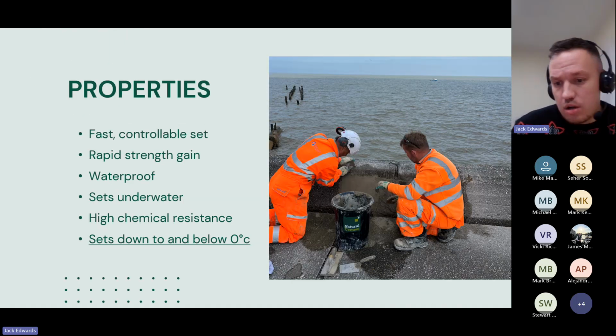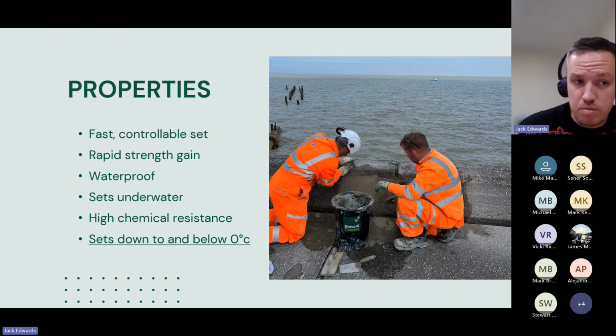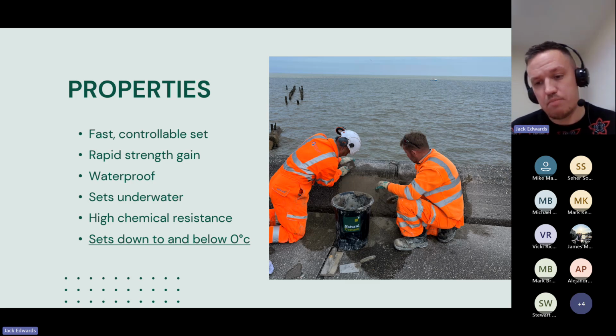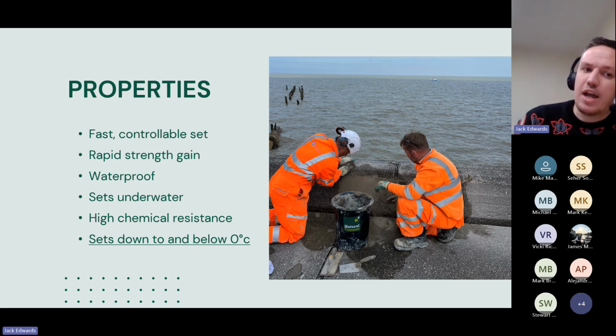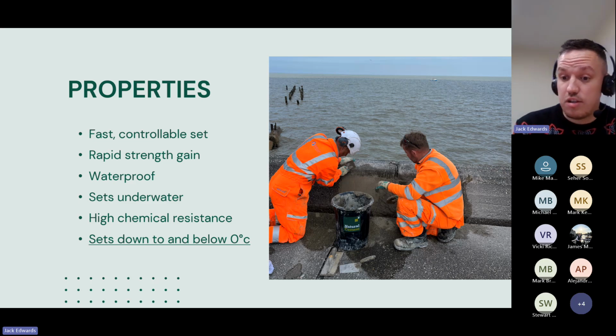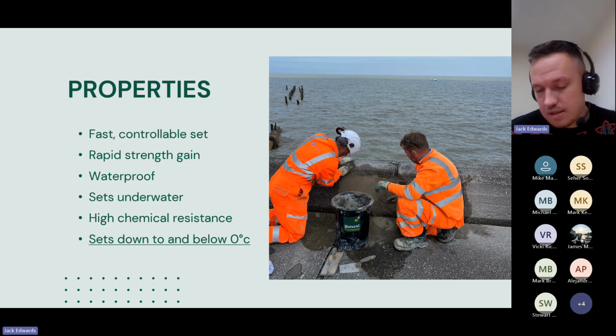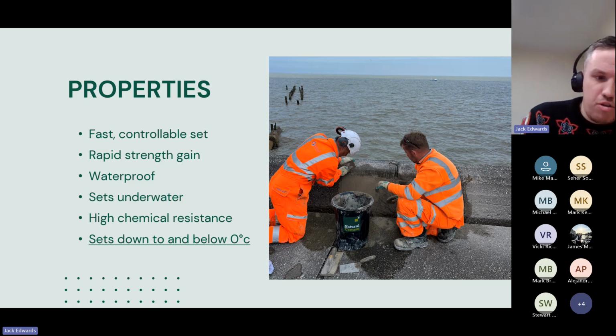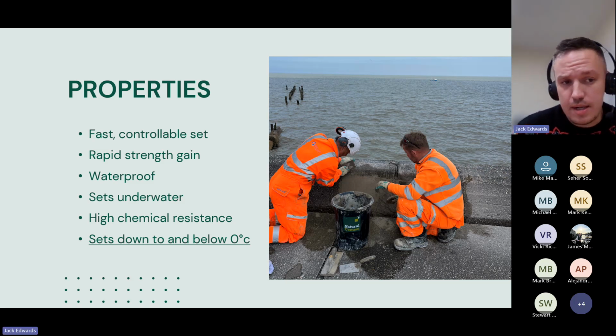Here are some of the main properties that we get from a natural cement. The first is a very fast set. Once the cement has been produced and ground to a powder, if you add it to water, the natural setting time is around 90 seconds to 2 minutes. So it's very, very fast setting, without need for any accelerators or anything to speed up that process. We've got a product called Water Stop, which is a plug for sealing against leaks. Like I said, that is our natural cement in its raw form. That will set in around 90 seconds to 2 minutes once it's been added to water.